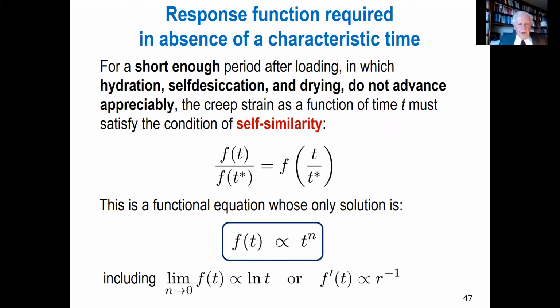Next, we deal with data. Data, unfortunately, are collected for different concretes. We can never get enough data in one lab, so we take data from the whole world, from many labs, measured on different concretes, behaving qualitatively similarly, but quantitatively different. And people in different labs measure differently, and that needs to be corrected. They introduce errors, and these need to be sorted out. Now, it has to be corrected based on what we theoretically know.